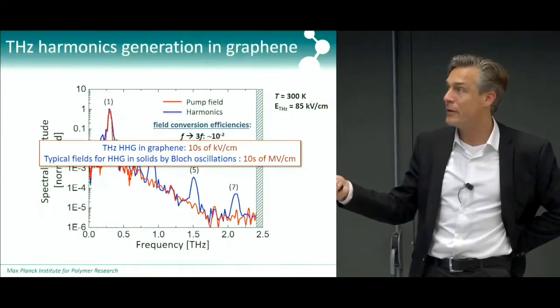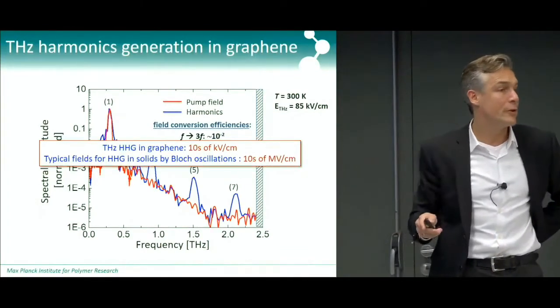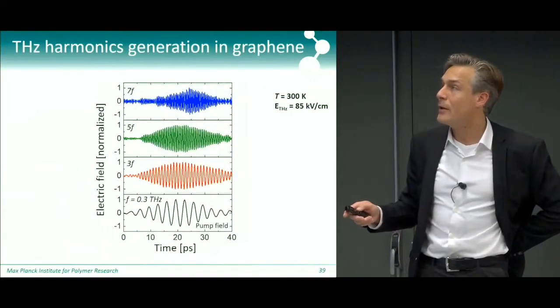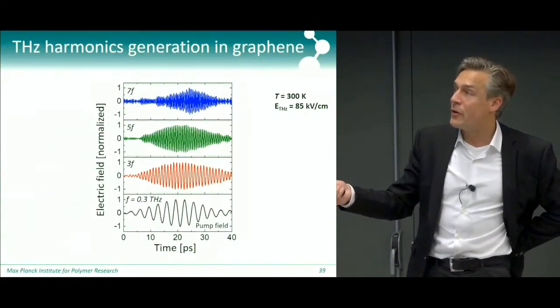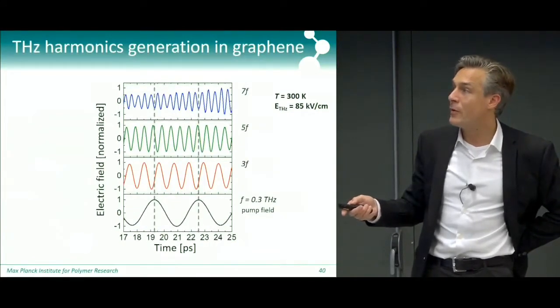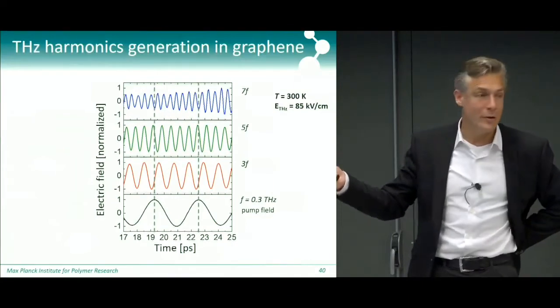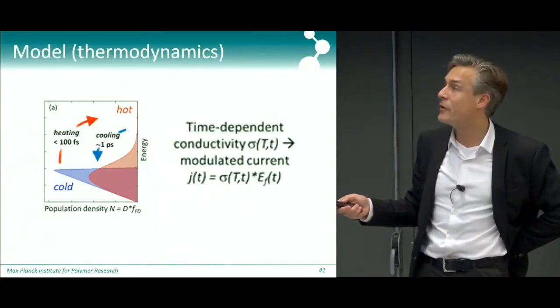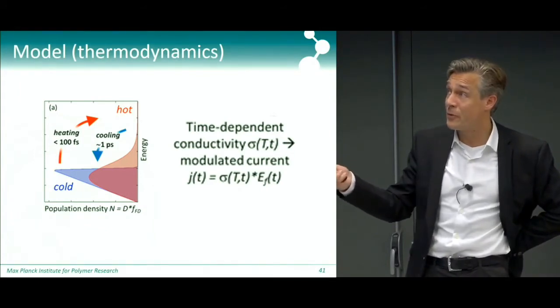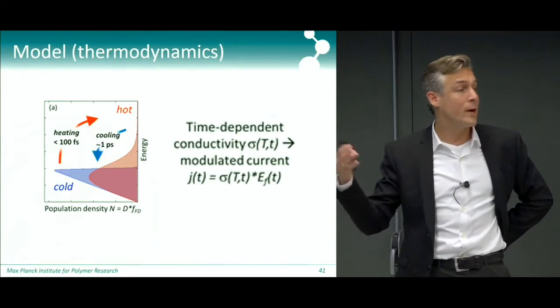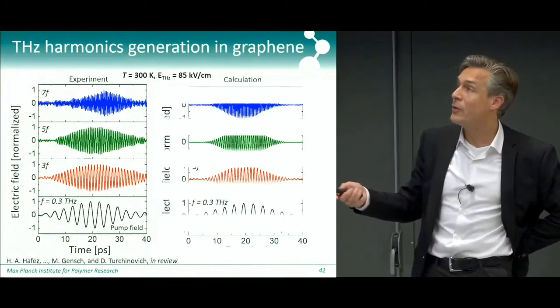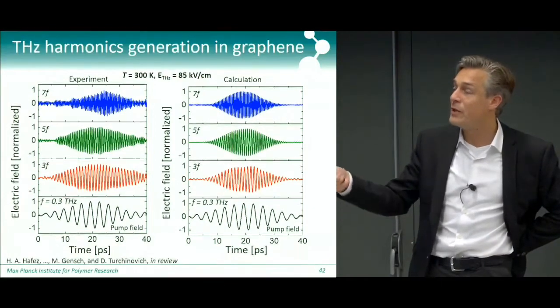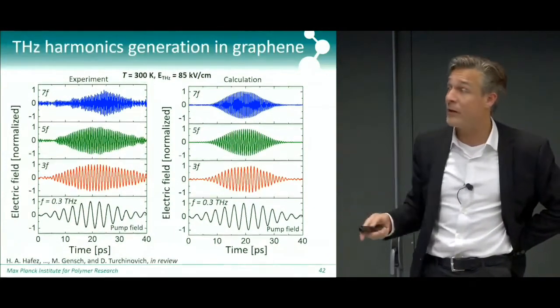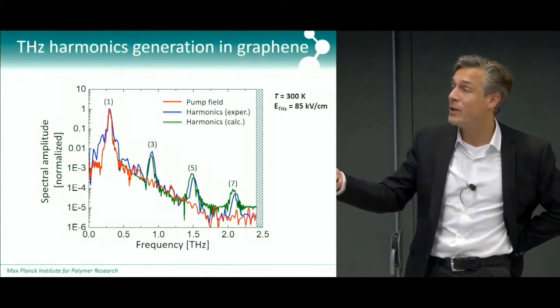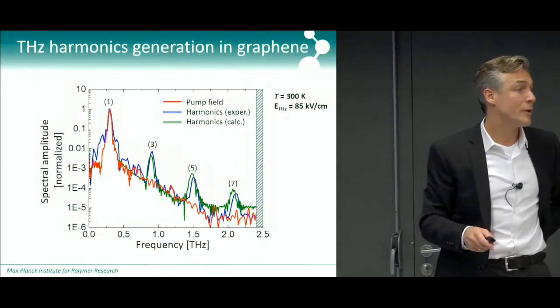And so if you compare that to what you would need for other types of mechanisms, you're orders of magnitude more efficient here. So these are the inferred third, fifth, and seventh harmonic fields. We can actually understand the phase relation between these different fields. We can also understand, again, through this simple thermodynamic model of heating and cooling and knowing how the conductivity changes when the heating occurs. We can model this, and I don't want to go into too much detail, but you can see that we really understand what is happening, and we can really quantitatively reproduce the harmonics that are being